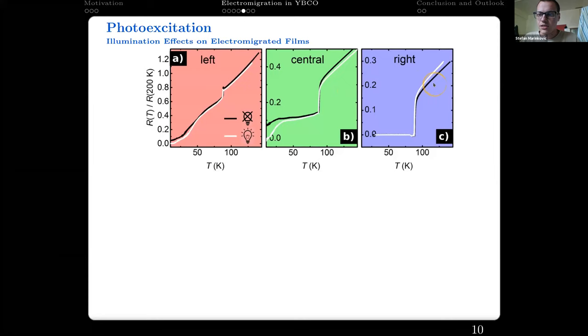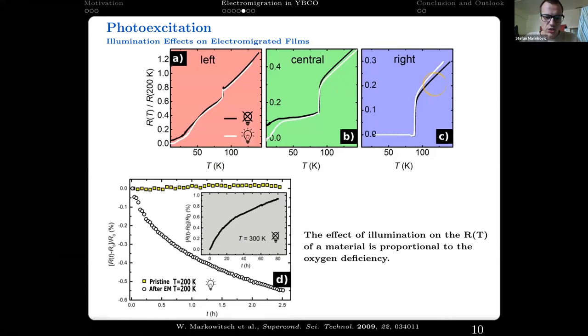If this, like the reference I mentioned, Markowitsch et al. write, is an effect that has a very long relaxation time. So if you take a look here, over time, as we illuminate the film, the resistance drops. But after turning off the light, if the film is not electromigrated, there is no change through illumination. But if you illuminate an electromigrated film, there is a drop in resistance. If you turn the light off and warm up, the change of resistance is on a much longer time scale, on the scale of days and weeks.